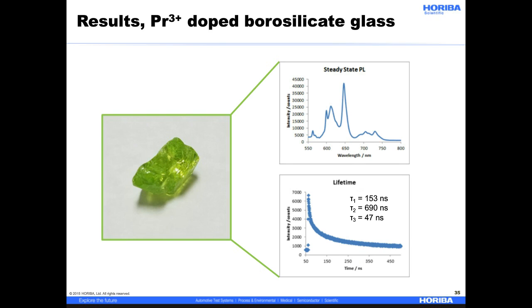The second set of results were recorded with a sample of praseodymium-doped borosilicate glass. In this case, the steady-state spectrum is shown in the top graph, and the lifetime recorded at a single point is shown in the bottom graph. From the introductory slides where I discussed another example of a rare earth-doped sample, you'll remember that there were several electronic transitions as indicated by the resulting photoluminescence spectrum. Although I have not assigned electronic states in this sample, you can see from the steady-state spectrum that it appears as though there are multiple electronic transitions as indicated by the multiple PL peaks.